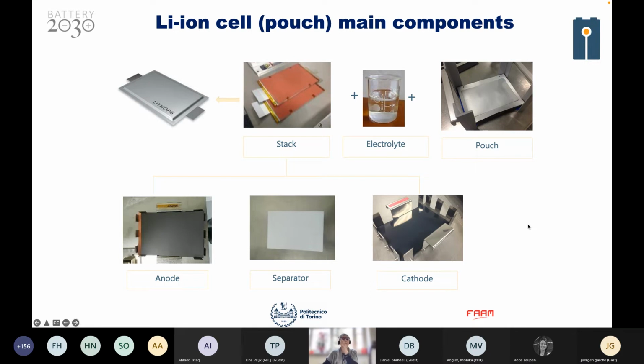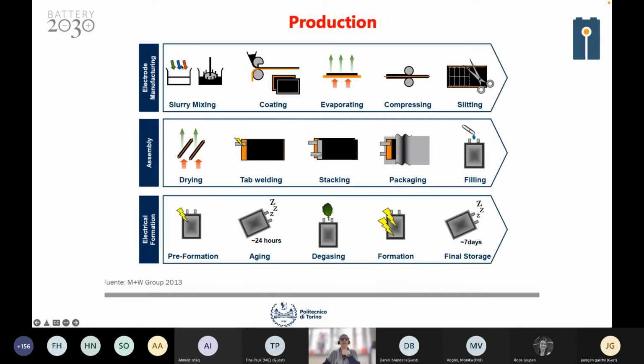Very briefly, as time is running very fast, the production of a lithium ion cell passes through different steps. The first step is the mixing of the active material with the carbon black, and eventually additives, and of course a binder. The binder is used to keep the particles attached one with the other and then on the current collector. Then we have the coating, so that the slurry produced by mixing is deposited on a film of the current collector moving through an evaporating chamber.